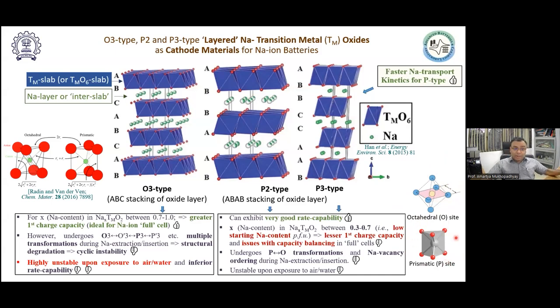So, but it cannot take up a tetrahedral coordination. Now, the possibility of sodium ion to take up a prismatic coordination surrounded by the oxygen ions leads to two predominant structure types for the layered sodium transition metal oxides. One in which the sodium ion has an octahedral coordination with the oxygen ions, and which leads to a O3